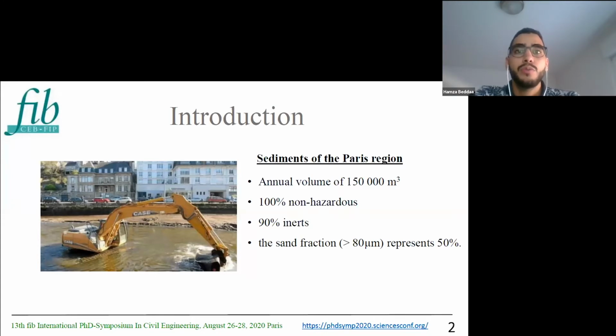These dredging operations, which are essential to ensure the transport of boats, generate an annual volume of about 150,000 cubic meters. So these materials are considered as waste, while the analysis show that 100% of these materials are non-hazardous and 90% are inert. And the sand fraction of these materials represents 50% of the total volume. So all this information favors the valorization of these materials in concrete as aggregates.